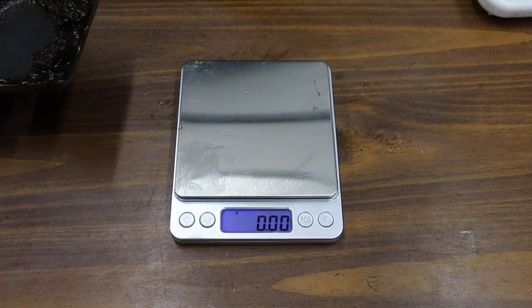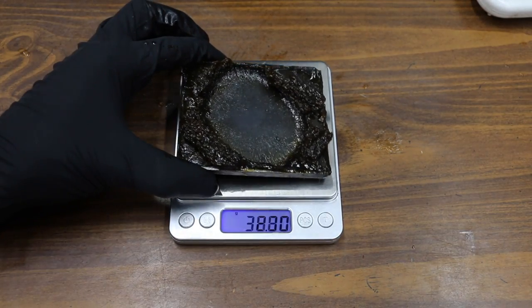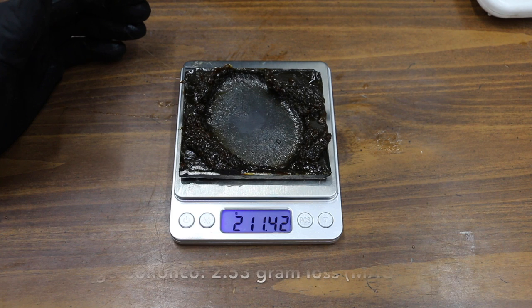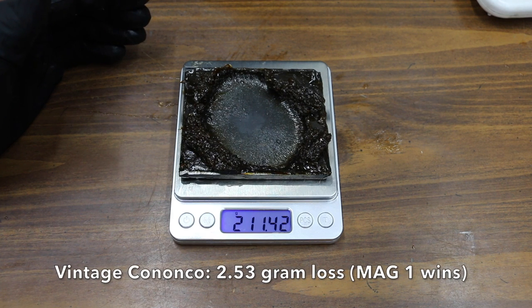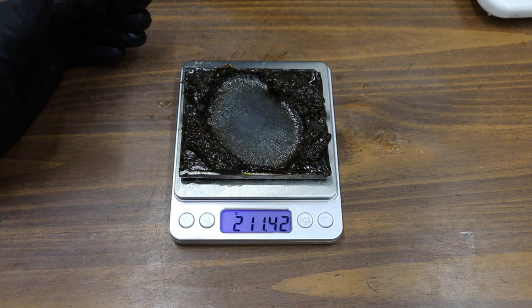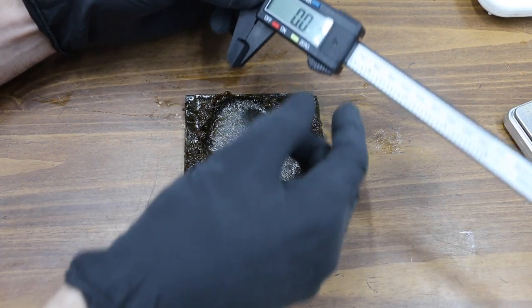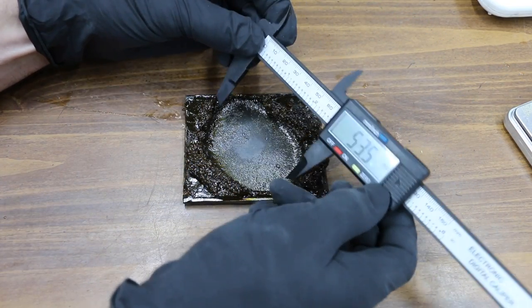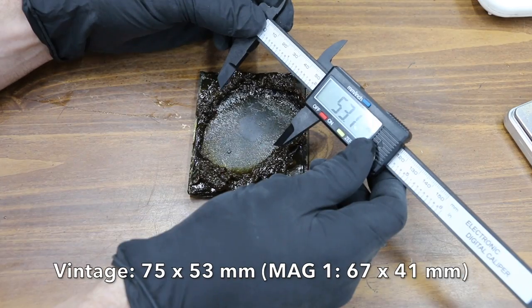The vintage grease started off at 213.95. It now weighs 211.42. That's a loss of 2.53, so the Mag 1 grease wins the showdown. Wow, that crater is huge. It did not do very good with the water wash-off test. The vintage grease is about 75 by 53.